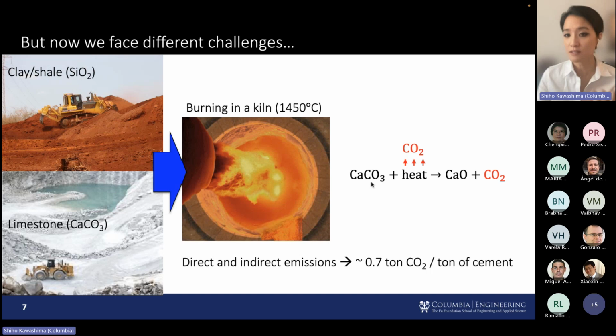And so we calcine calcium carbonate, right? To obtain calcium oxide, which is the calcium that we want for Portland cement or clinker. And just through the chemistry, there's direct emission of CO2. And of course, the calcination is done because we burn the material, right? And so we burn this massive cement kiln to temperatures of 1450 degrees Celsius. And so, of course, there's thermal emissions associated with this, where we utilize fossil fuels.